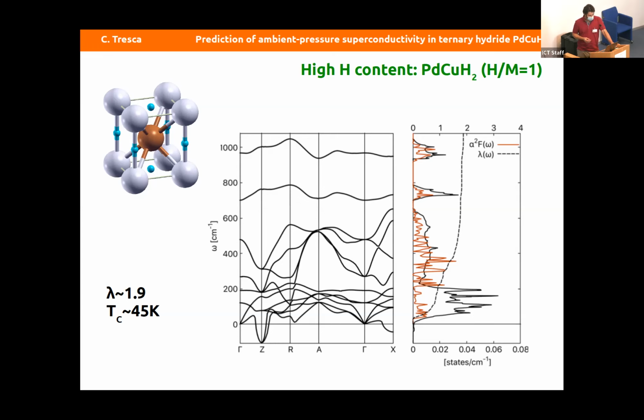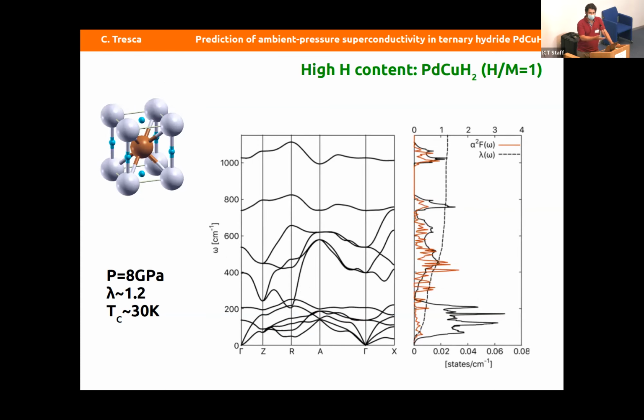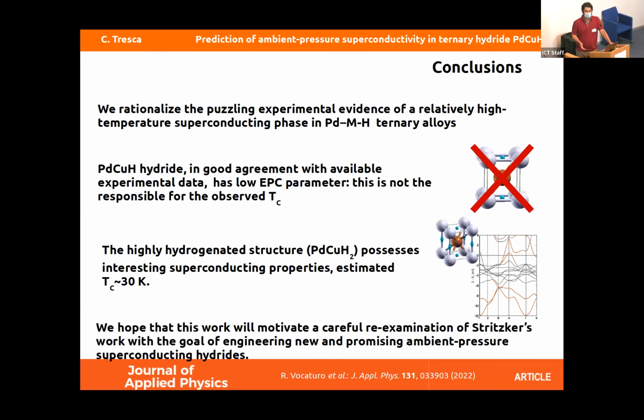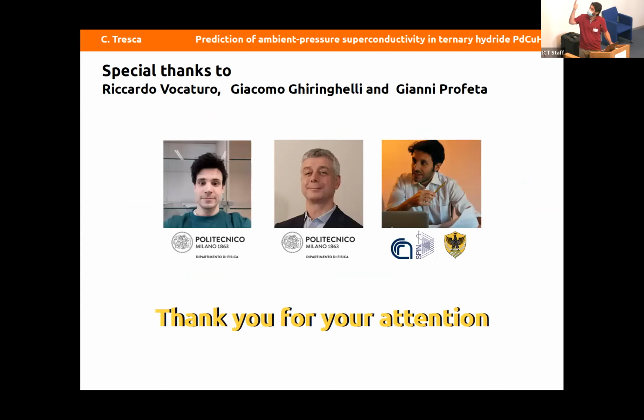Of course, in this kind of compounds, the anharmonic effects are important, as demonstrated for palladium hydride and so on. So we try to mimic the contribution of anharmonic effects by applying a low pressure to this structure, able to dynamically stabilize the structure. Of course, there is a decrease of the electron phonon coupling and of the critical temperature. But probably this is the phase realized by Stritzker. So in conclusion, we studied the ternary palladium copper hydrides, probably understanding what happens in the Stritzker experiment, and we hope that this study will motivate a re-examination of this experiment. Thank you for your attention, and thanks to the collaborators.